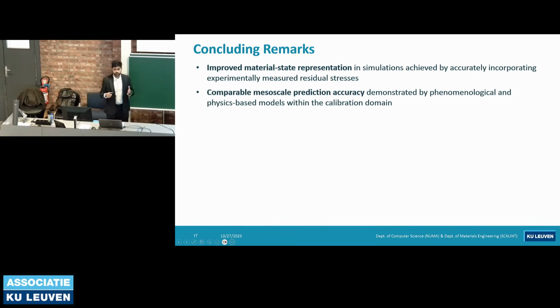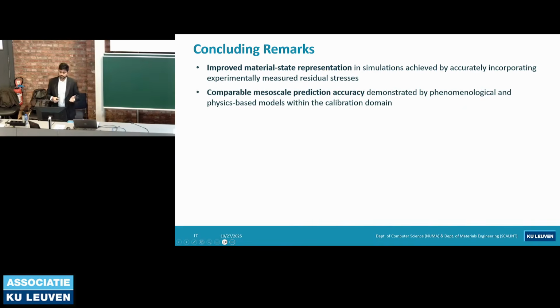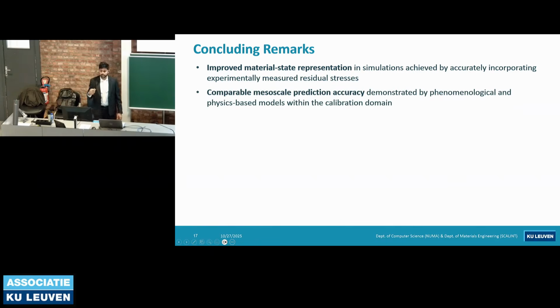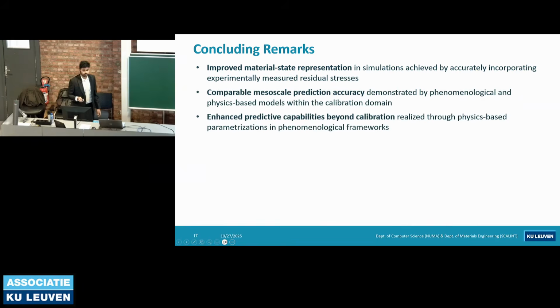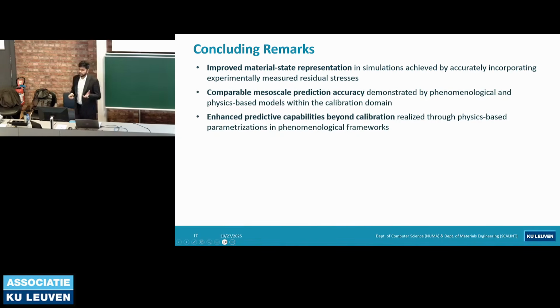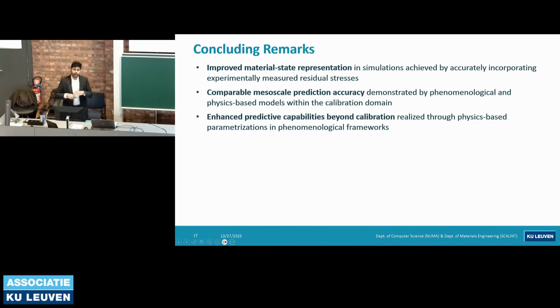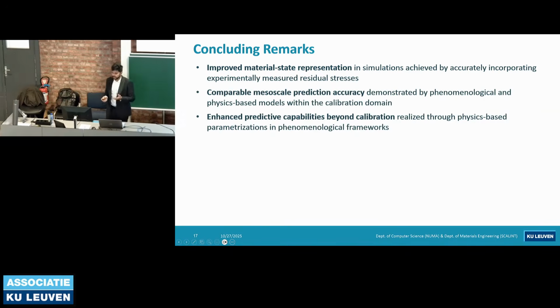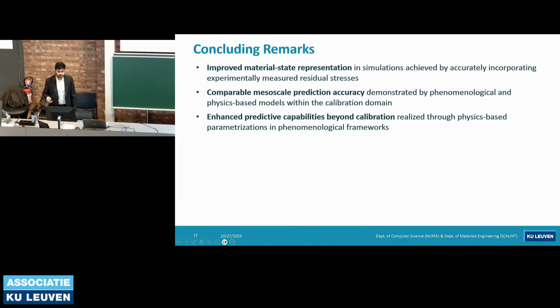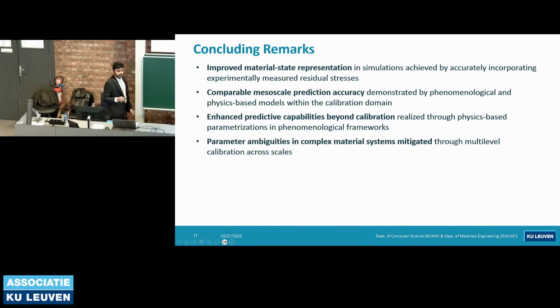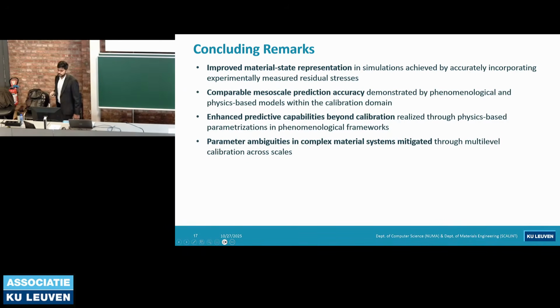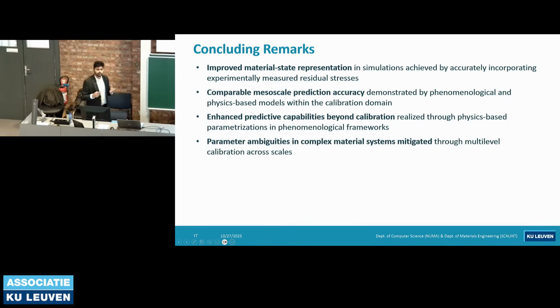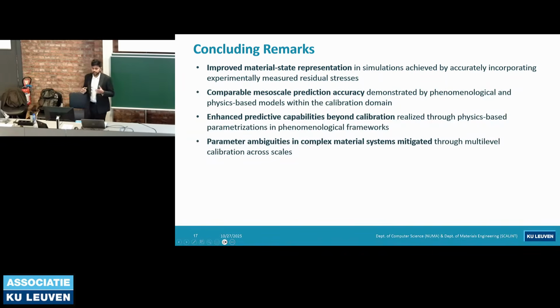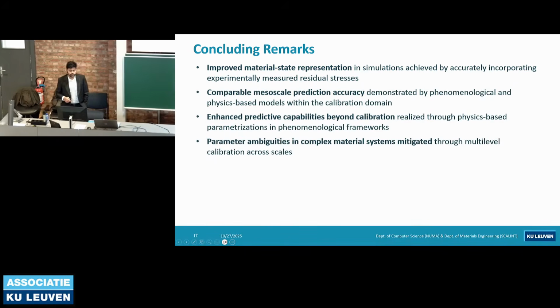Next, we compared two different models, one phenomenological, which is operationally quite efficient, and the other a dislocation density based model. And it was seen that within the data domain of calibration, phenomenological models perform comparable to the dislocation density based one. Next, we tried to enhance the predictive capabilities of this phenomenological model by using physics-based insight, and the focus was outside the data domain of calibration. We did that with the help of incorporation of physics-based interaction coefficients. And for a complex deformation system, such as hexagonal close-packed titanium, using this multi-scale parameter calibration, we tried to mitigate the parameter ambiguities that are often seen from the data published in the literature.